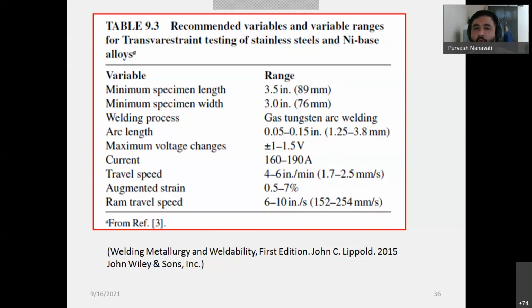Now, maximum voltage changes from 1 to 1.5 volt. Current is ranging from 160 to 190. Travel speed is 1.7 to 2.5 mm per second. And augmented strain is 0.5 to 7%. Sorry. And this ram travel speed, bending, it is 150 to 254 mm per second. Okay, so for knowledge, these are some welding parameters for conduction of the test.